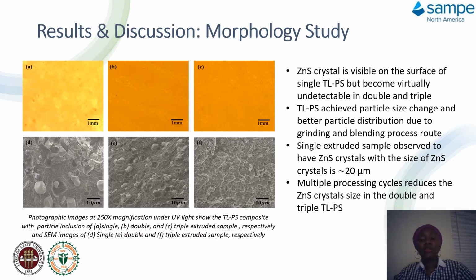And when it goes to the third process, the multi-processing cycle affects the crystal, makes it more evenly dispersed within the composite, and much smaller than in the first and the second process. With this processing cycle, we were able to achieve a better particle distribution, and it also helps to reduce the sizes of the crystals within the composite.